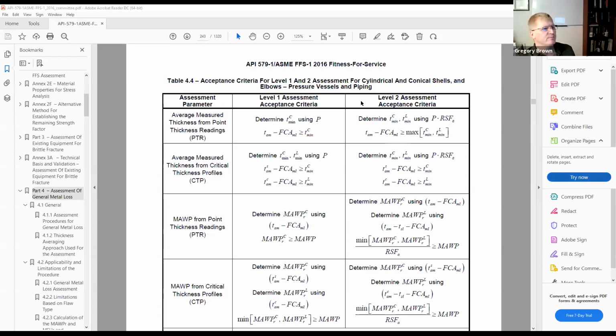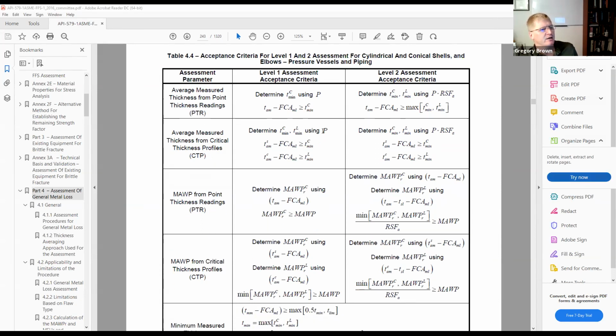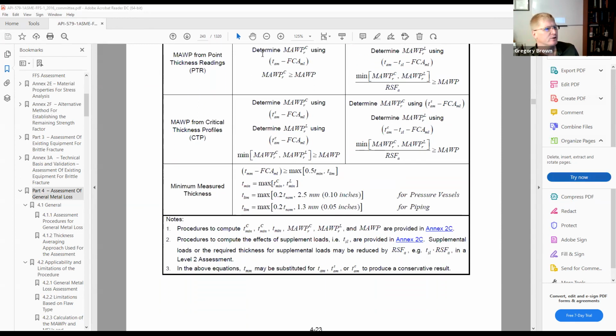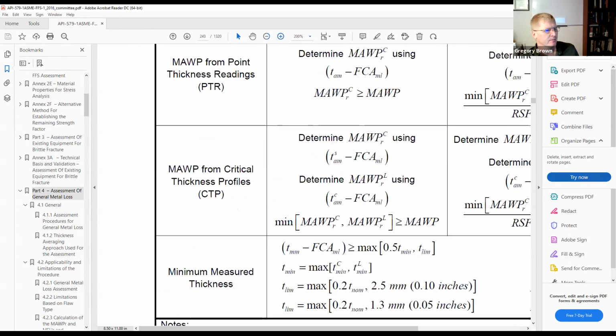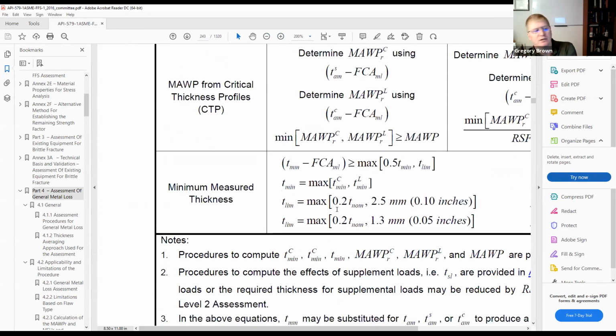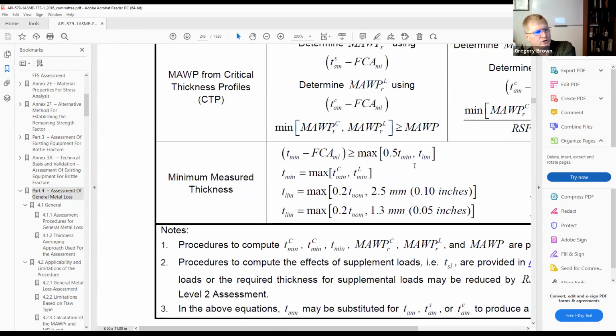So to answer your question, for example, if people can see that, I know this is probably a little challenging to see. This is from part 4 of 579. These are all the rules. We'll talk about these in the course. But at the bottom, you see that the minimum measured thickness has to be less than this limiting value, what you're talking about. So you have to have at least half the design minimum or this limiting value, which you see is 0.2 of nominal. So 0.2 of nominal means I have 20% of my wall left, which means I've lost 80% of my wall. Does that answer your question?